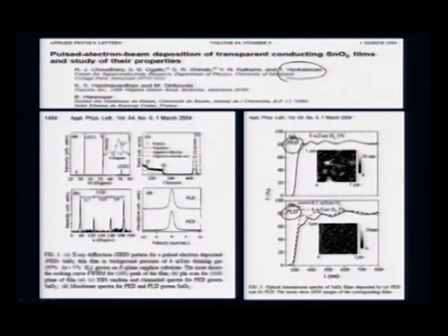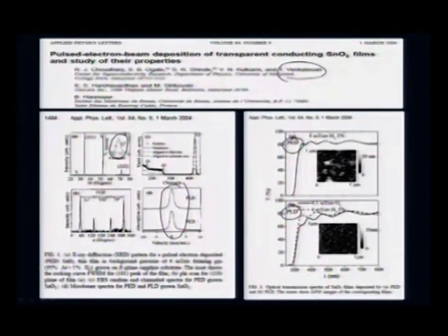And here you also look at the mapping of your tin oxide using Mössbauer. The isomer shift is exactly the same between PED and PLD. That means you can get a very well oriented film. And here again in B you can see the phi scan of all the reflections of tin oxide, and the rocking curve shows that the full width at half maximum is less than 1 degree. That means it is a very nicely grown film using the PED method.